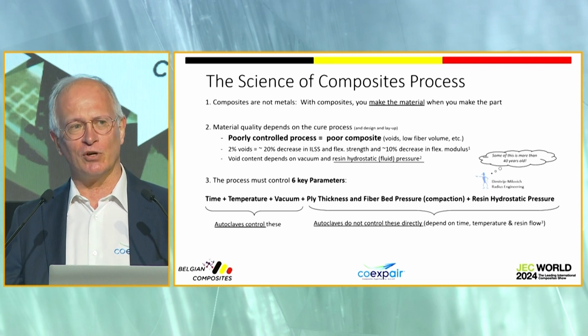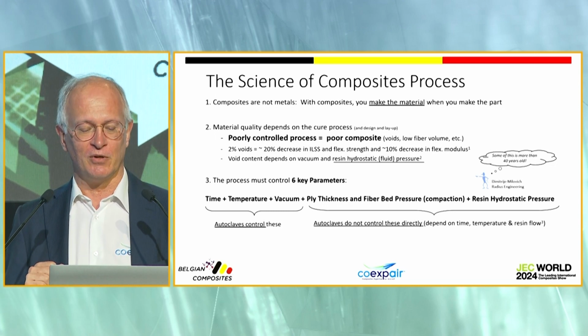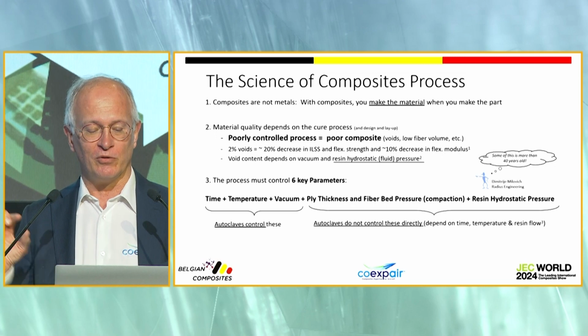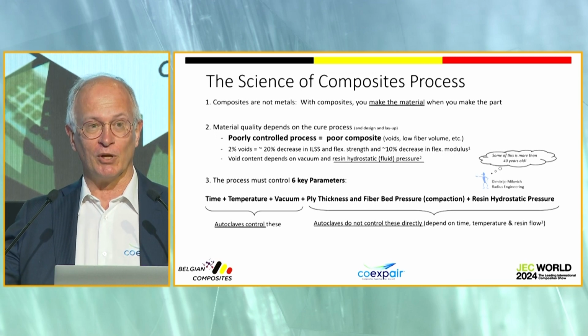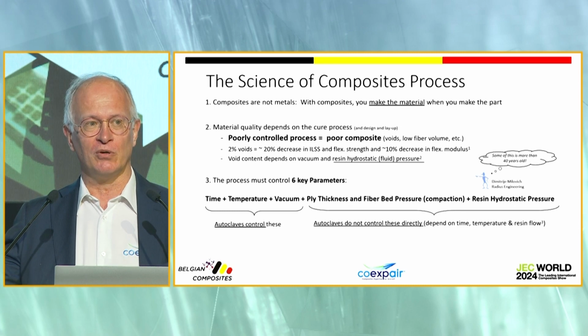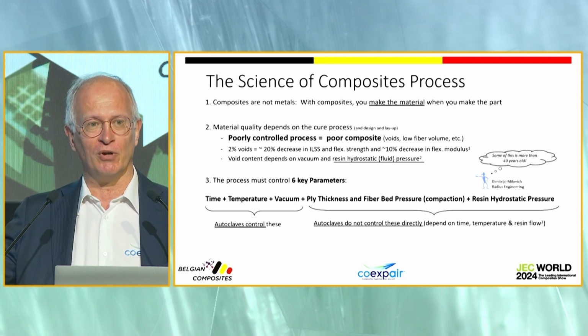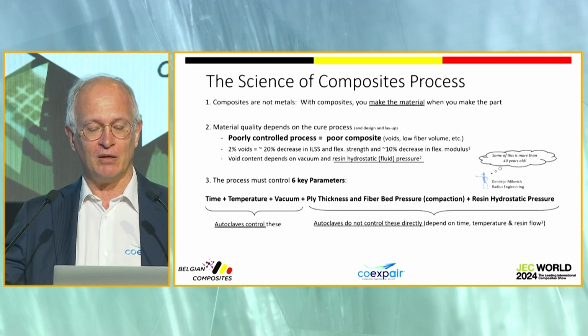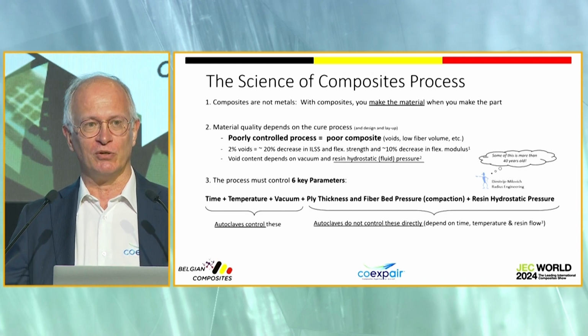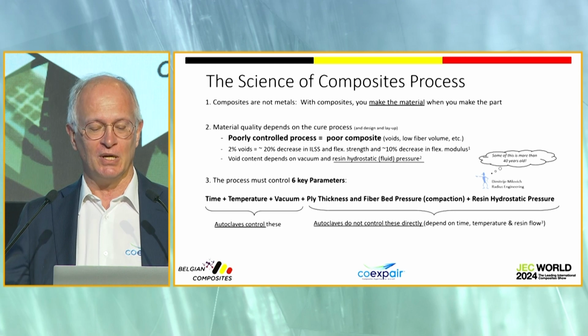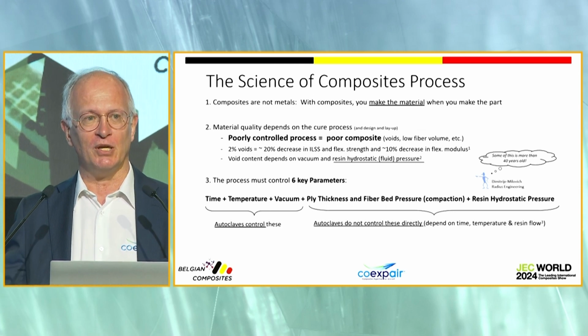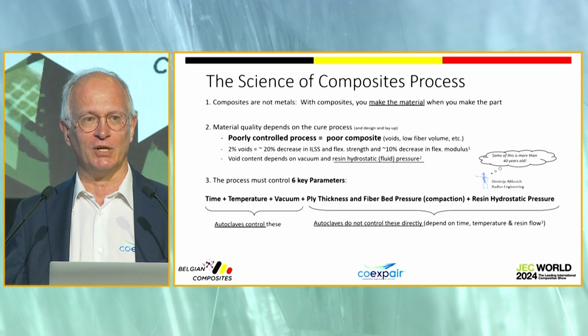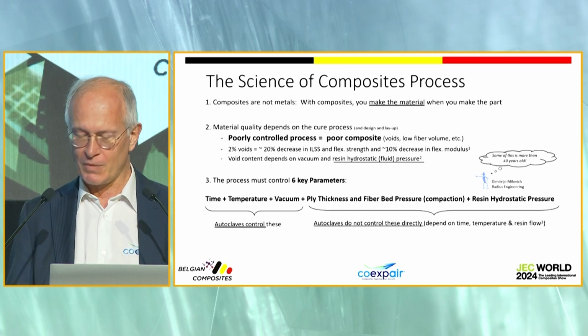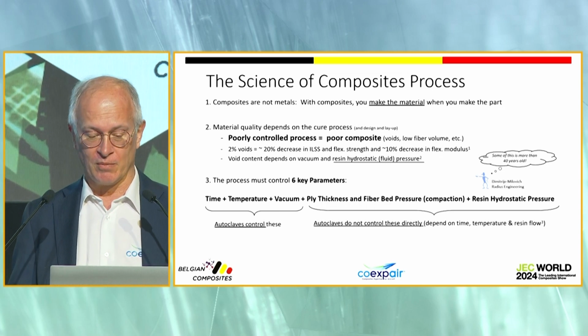Autoclave controls these parameters. But the other parameters, the ply thickness, really what will be the thickness of your part, the fiber bed pressure, the pressure on the fiber, on the laminate, and the resin hydrostatic pressure, the pressure in the resin, have to be controlled independently. And that does not work in an autoclave. And it will never work.